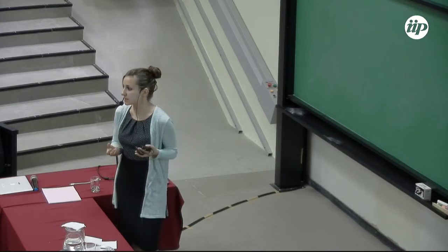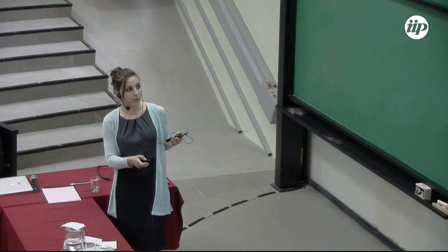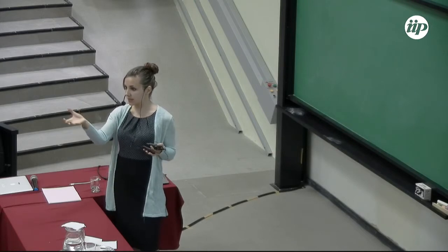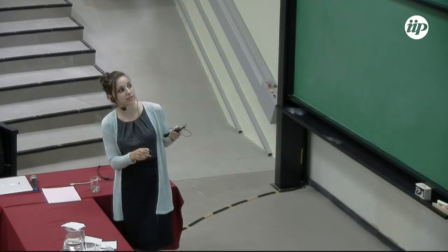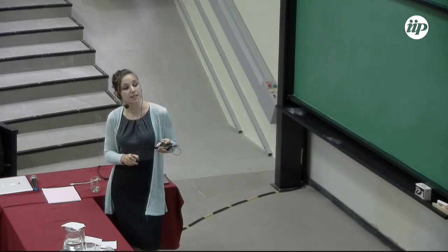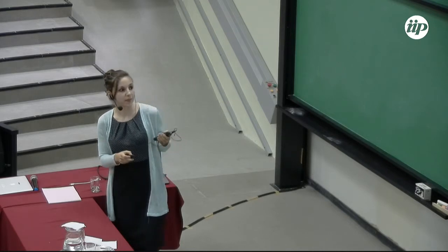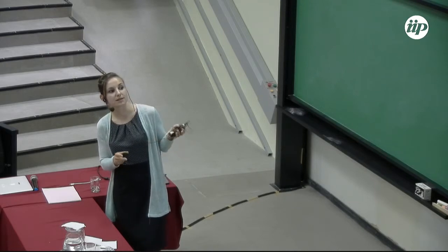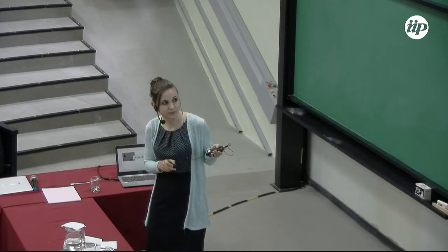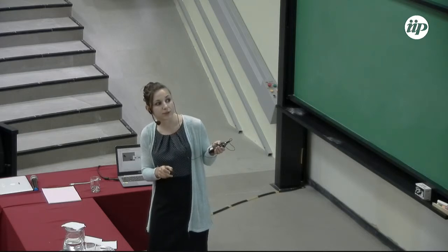So if we just have these particles in water and we don't have any active compounds, then what we see in a microscope is just these black circles, simply because the platinum would orient cap down and absorb all the light. But once we add peroxide, the particles get activated. They change their orientation, so that depending on whether you think in a real world or in a vector world, this is a 90 or a 0 degree orientation. And we basically see half a cap and half an inert cap.